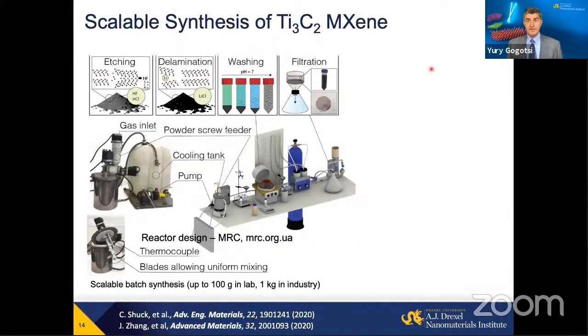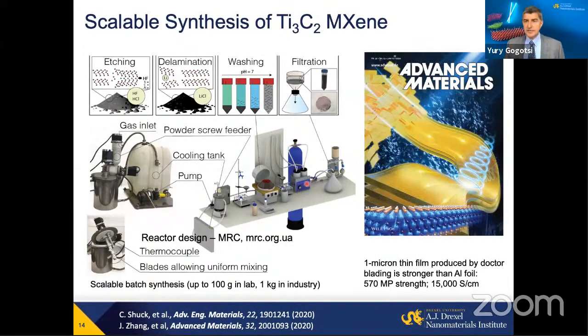And here, actually, graphene, clays, molybdenum disulfide, tungsten disulfide, and boron nitrides form a very small group of materials where significant amounts can be produced. What is important, because of this, MXene synthesis by chemical etching of ceramic powders, basically MAX phases, we were able to make grams of material from pretty much day one. We can make up to 100 grams in a run in the reactors that we have in the laboratory now, which were designed for us by MRC. And there are kilogram-size reactors in industry. So it's an intrinsically scalable process.